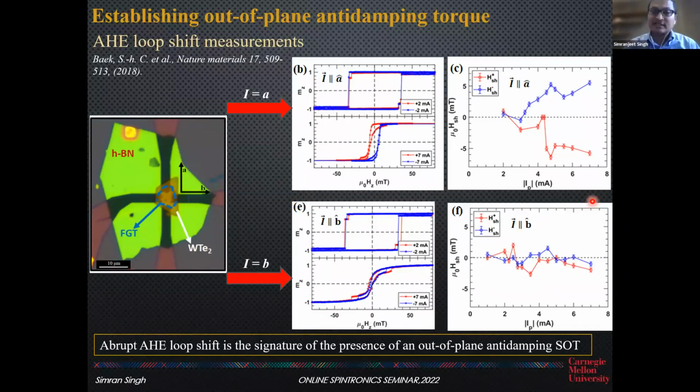That's a very interesting question actually. We do see a small change in the longitudinal resistance RXX along the A axis and B axis, but we don't see much change in terms of RXY. Honestly, we haven't looked that carefully at RXY, but we looked very carefully at RXX, the longitudinal resistance, and we see a small difference between along the A axis and along the B axis.